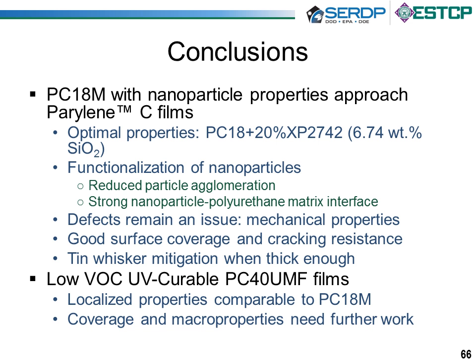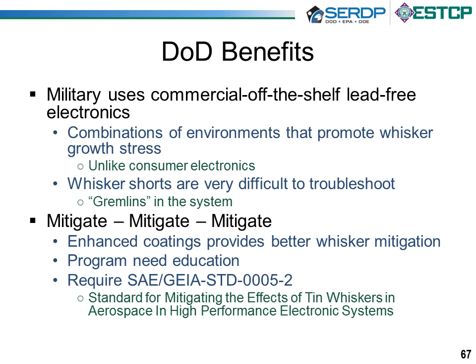So getting it thick enough continues to be important. The low VOC, we have some indication local properties are comparable to PC-18M with nano indentation, but coverage and macro properties still need some work there. And from the DoD benefit side of things, military leverages significant cost benefits from using commercial off-the-shelf lead-free electronics.